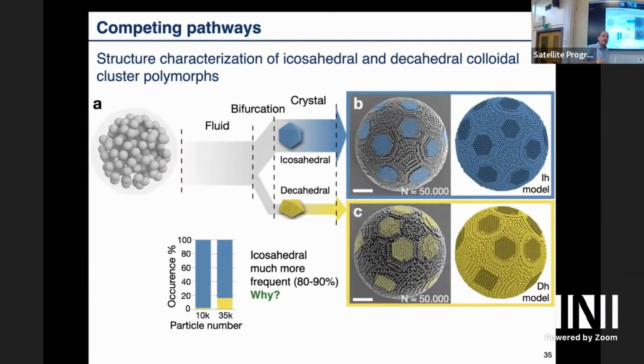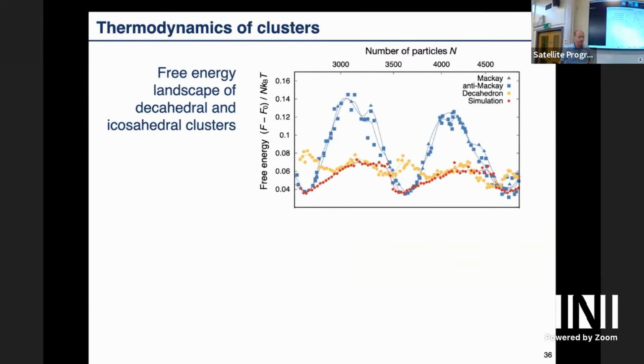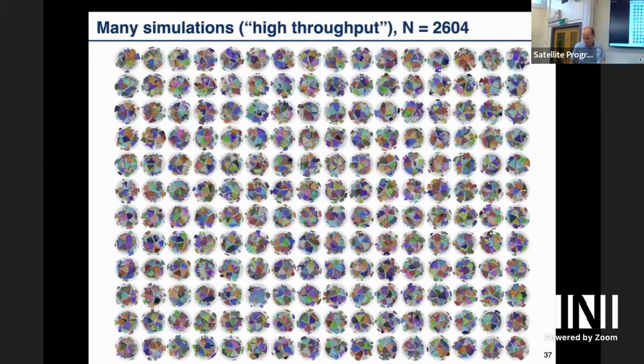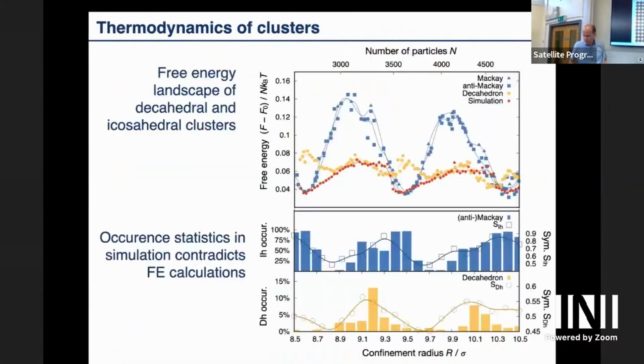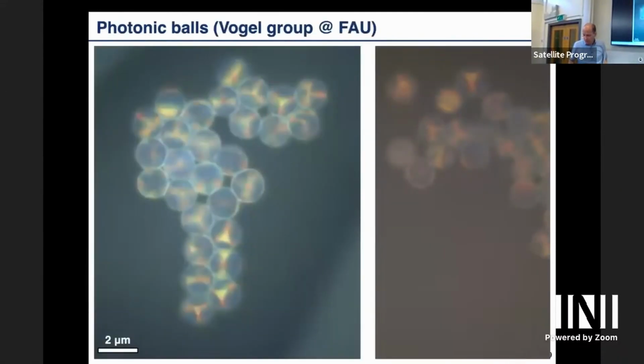And we can now go on and explain why they are rare. Just as a spoiler, it's not thermodynamics, because as you see here, the decahedral clusters can sometimes be even more stable. So yellow is below red, and red is below blue. Blue is icosahedral, yellow is decahedral, but it has to do with kinetics. You can study this quite in detail and explain why different symmetries appear. I will just skip through this, and if you're interested, just talk to me and I can give you the preprint. We can explain why they work.